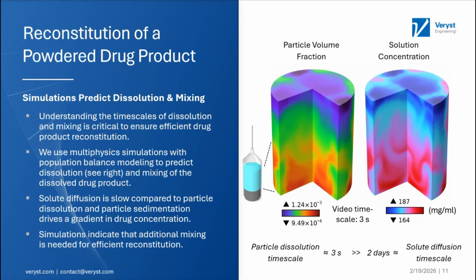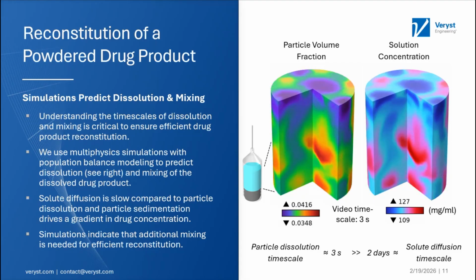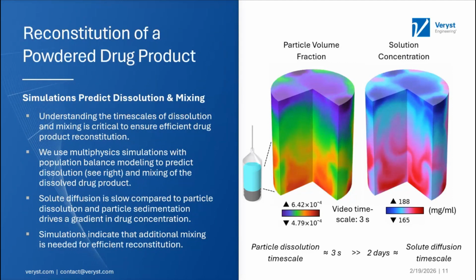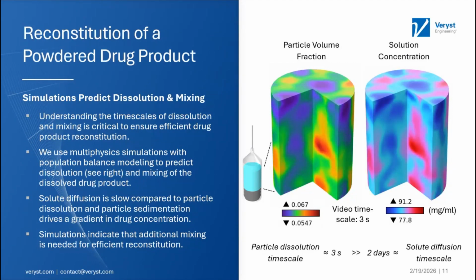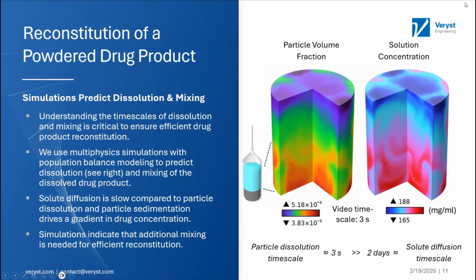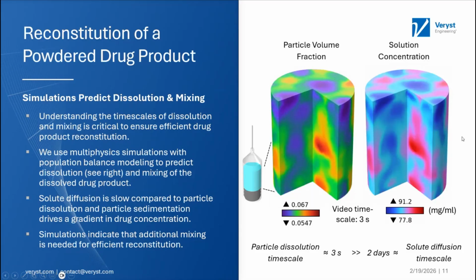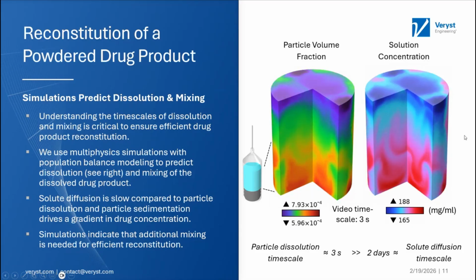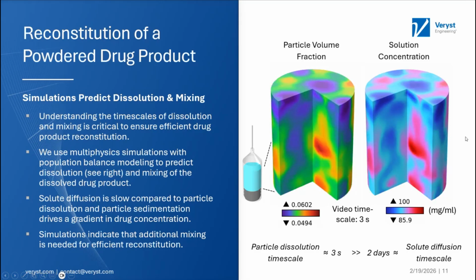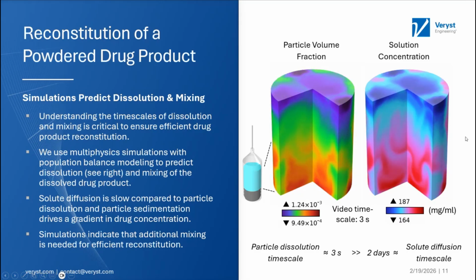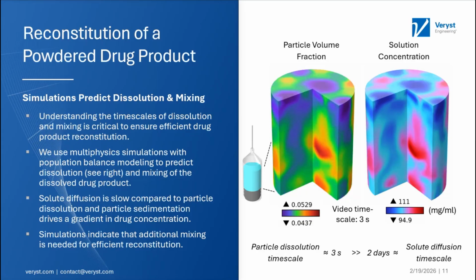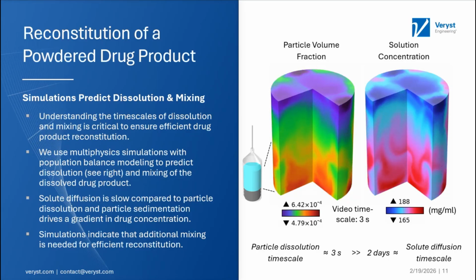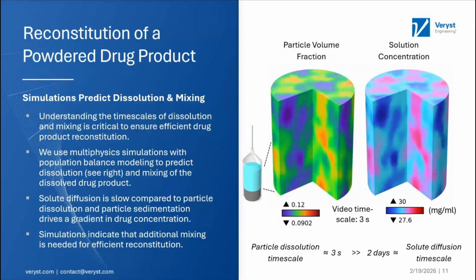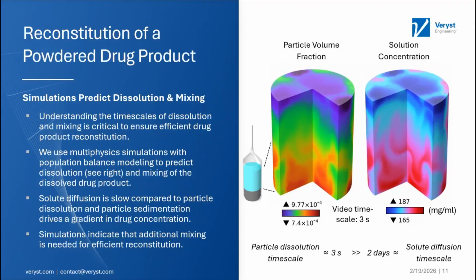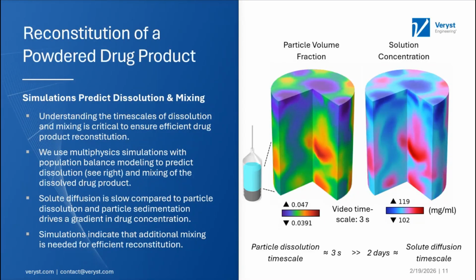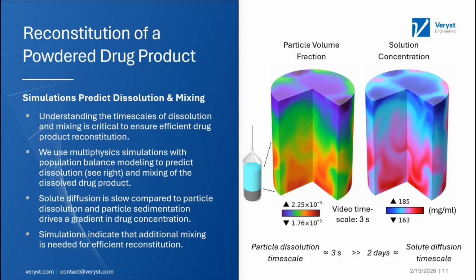The solute diffusion is slow, on the order of days, compared to the fast dissolution timescales, which are on the order of seconds. There's particle sedimentation, and you can kind of see that in the videos, and this is due to gravity, and this creates a vertical concentration gradient. These simulations indicate that additional mixing, for example, swishing the syringe, would be needed to quickly homogenize the solution on an efficient clinical timeframe. But simulations such as these can help design device usage protocols depending on the formulation.